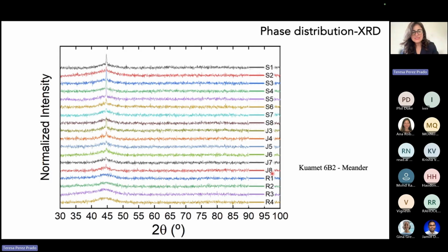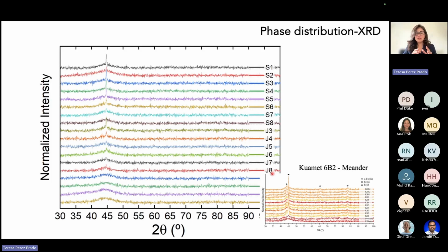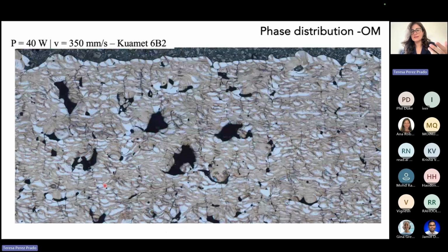I know this is a lot of data, but my message here is that I would like you to compare these XRD patterns with the ones we were getting in the commercial alloys when we were using the simple scanning strategy. So now, even though for some conditions we didn't fully get rid of the crystalline peaks, if you compare here, already by XRD, we can see that the crystalline fraction is much smaller. And for some conditions, they are completely amorphous, at least XRD amorphous. But we wanted to check that using other techniques.